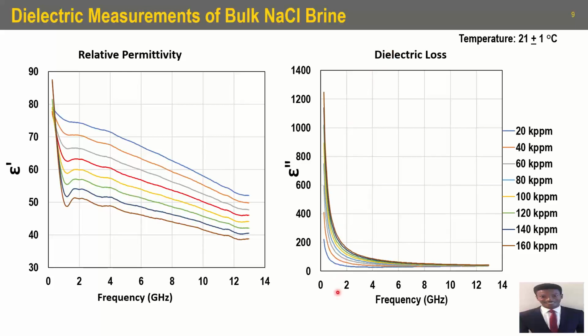Meanwhile, when you look at the dielectric loss as a function of frequency, you would see that there is a great deal of dispersion for the various brine concentrations considered. So based on this, we can go ahead to use this dielectric loss measurements, which we've shown earlier to be a function of conductivity, in order to infer what our salinity could be.